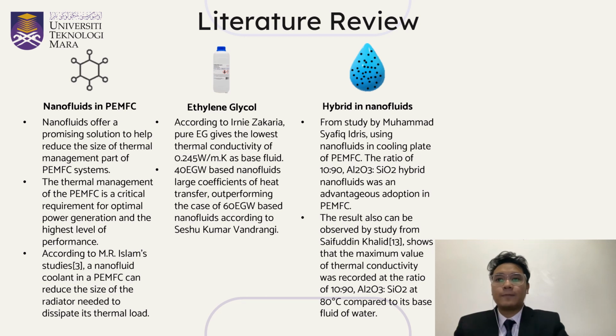fluid of water. The result can also be observed by the study from Saifuddin Khalid, which shows that the maximum value of thermal conductivity was recorded at the ratio of 10-90 Al2O3 SiO2 at 80 degrees Celsius with 51.9% enhancement compared to its base fluid of water. This paper summarized that the 10-90 ratio of Al2O3 SiO2 hybrid is the most feasible ratio for the implementation in PEMFC.